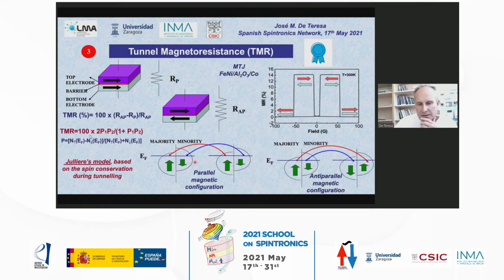For that, he just had to assume that in the parallel magnetic configuration, the electrons from the spin up subband tunnel to the available density of states in the spin up subband of the second electrode. This is one current, and you have to add a second current, which is the current from the spin down subband to the available density of states of the spin down subband in the second electrode. Okay. What about the antiparallel magnetic configuration?